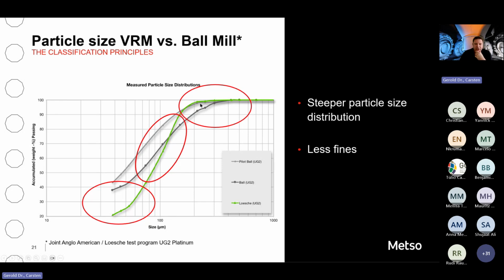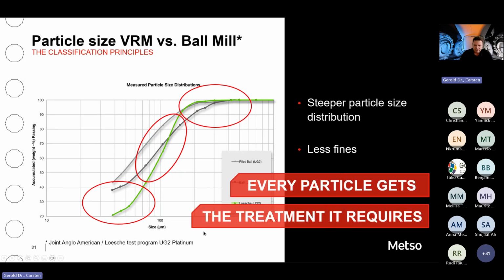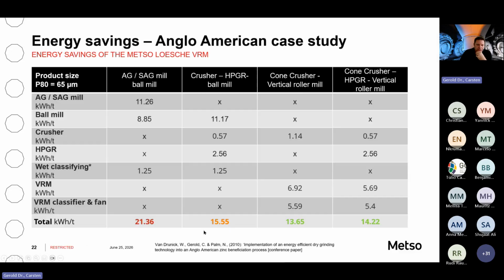And that's changing your degree of liberation very much, because you can imagine in that coarse area here, there's still intergrowths between your valuable minerals and the gangue material. But with that direct classifying we have, we get a very efficient classification, so a steep classification. And therefore, these product particle size distributions look different. And if it's steeper, it's easier to adjust your downstream process. So every particle gets the treatment it requires.